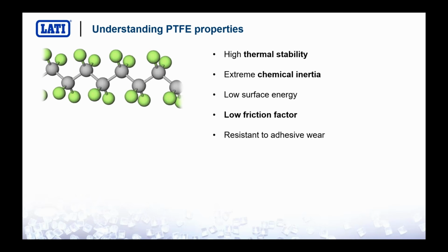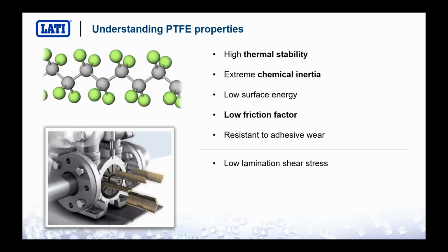So the forces between the polymeric chains are weak. That's the reason why, in order to laminate it, you don't need a big energy, a big work. It's easy to shear the molecule, to laminate it. That's the reason why PTFE, even though it's a strong material, exhibits a very low abrasion resistance. In fact, there are many solutions to improve it, for example, a solution with the synergistic effect between PTFE and aramid fiber.